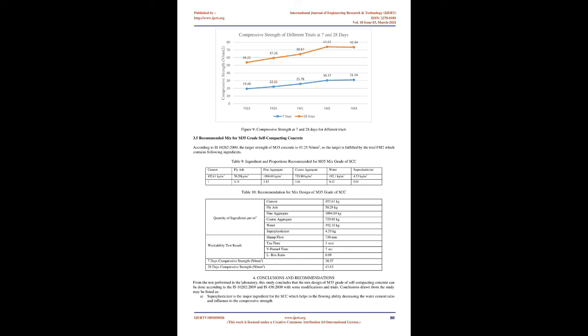Similarly for the 28th day result, all trials except FM2 fail to obtain the target strength, 43.25 N/mm2. It may be because of higher water-cement ratio and the paste flowing away. Thus trial FM2 can be considered as the best mix for the M35 self-compacting concrete from the ingredients used for the study. Recommended mix for M35 grade self-compacting concrete. According to IS 10262:2009, the target strength of M35 concrete is 43.25 N/mm2, so the target is fulfilled by trial FM2, which contains the following ingredients. Conclusions and recommendations.